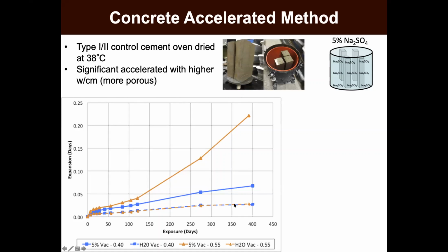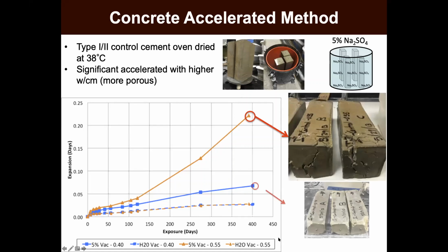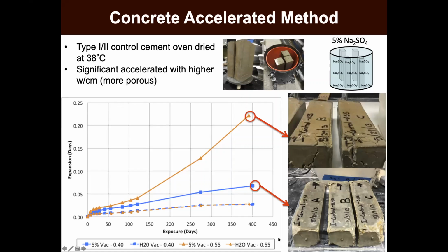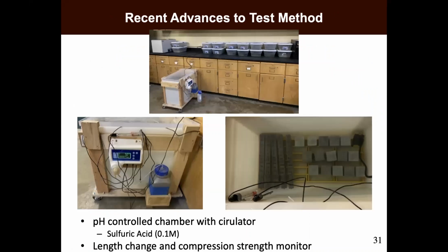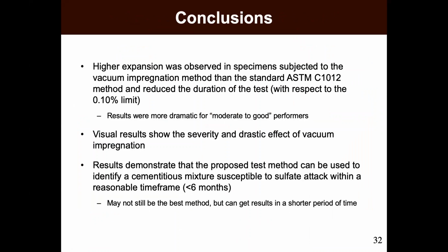When looking at the typical without vacuum impregnation versus with vacuum, we have much faster results. Right? So we have a much faster deterioration. So I'll quickly head into the conclusions in this case. Again, we did see a much faster mortar deterioration with the vacuum impregnation method. The visual shows the results. I think it shows the severity and the drastic effect of the vacuum impregnation.